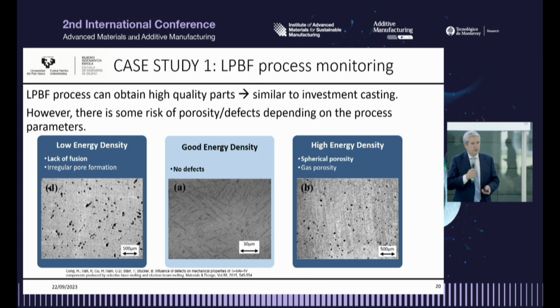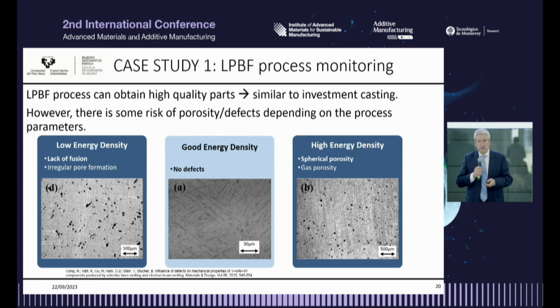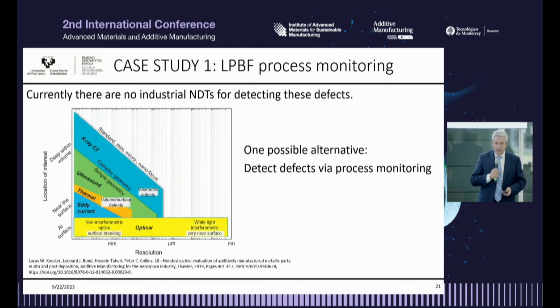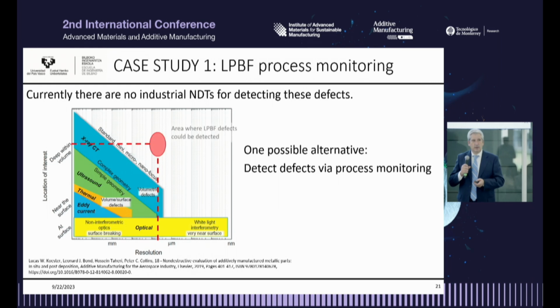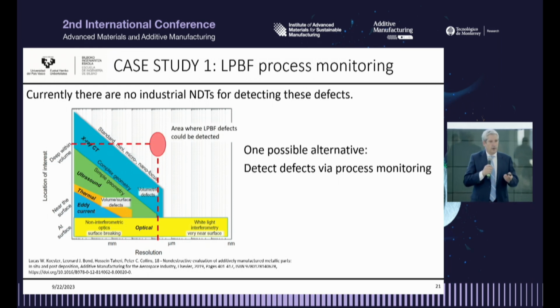good parts with no defects, as you can see in the center of the slide. But if we drop the energy density a little bit, or if we go higher with the energy density of the laser, we obtain porosity, in terms of lack of fusion or gas porosity. So we need to know if we have a good or bad part. The bad news is that currently there are no reliable industrial non-destructive techniques for measuring this effect. Why? Because at surface level we can go to a very small resolution, up to nanometers.